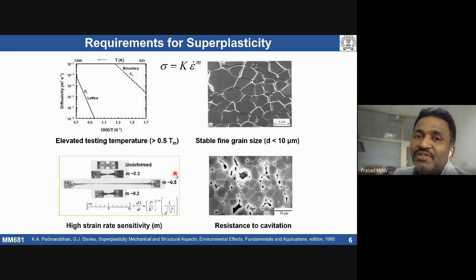These apply if you're talking about elevated testing temperatures, typically greater than 0.5 times the melting point. Stable fine grain size: for metallic materials, the grain size should be less than 10 micrometers. For ceramics, the grain size must be less than 1 micrometer.